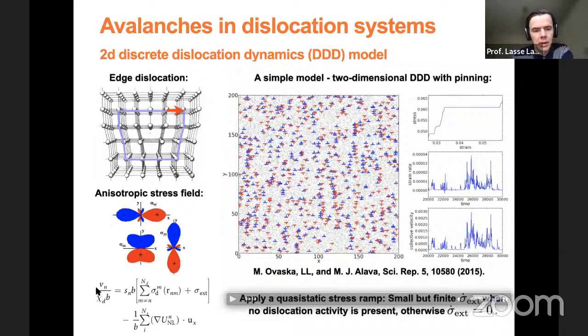They basically just say, okay, your velocity of dislocation is proportional to the total stress acting on it. And this can have contributions from the interactions and from the externally applied stress. And as a result, if you do the simulation, you get this kind of typical stress strain curve that looks a bit like the one that you get from these micropillar compression experiments. So you have this bursty deformation dynamics also from this model.